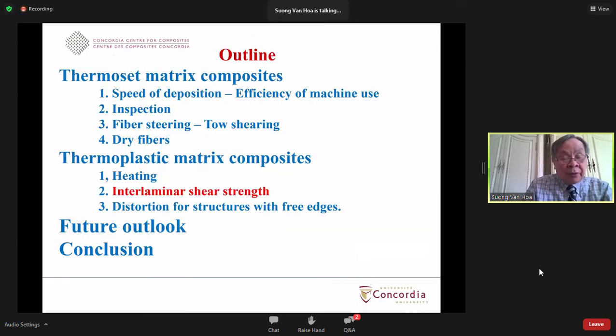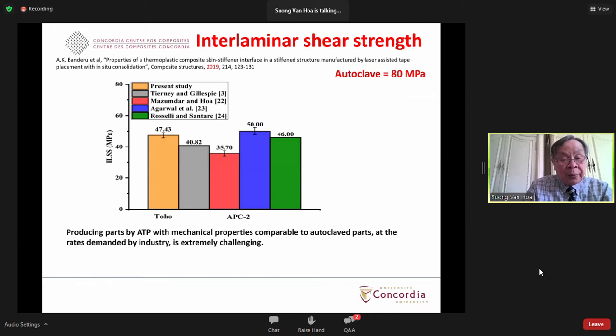Now, one of the issues with the thermoplastic composite is interlaminar shear strength. What I find is that the interlaminar shear strength of laminate made by thermoplastic composite is not as high compared to that of the autoclave. In a publication in 2019, there was a comparison between the interlaminar shear strength of laminate made by different kinds of AFP using different kinds of composite, and the value is around 50 MPa, compared to about 80 MPa. So that's roughly about 60% that of the autoclave.